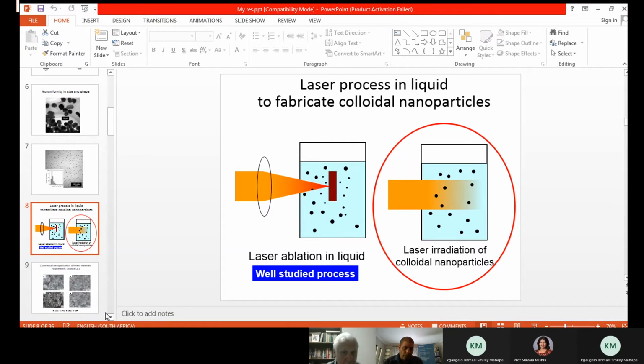But we have another possibility. Let's try to ablate colloid with nanoparticles with a non-focused laser beam. Why do we think non-focused? Because if we concentrate the laser beam in one point, the probability of interaction of this laser beam with nanoparticles becomes very, very small. Please imagine the laser beam concentrated in one point. We mix our colloid, so our particles move, but the probability that different nanoparticles meet the laser beam at this point will be very small. So it needs a long, long time for ablation. So our other idea: let's try to ablate this colloid by a non-focused laser beam and see what happens. Okay, let's move to the next slide.